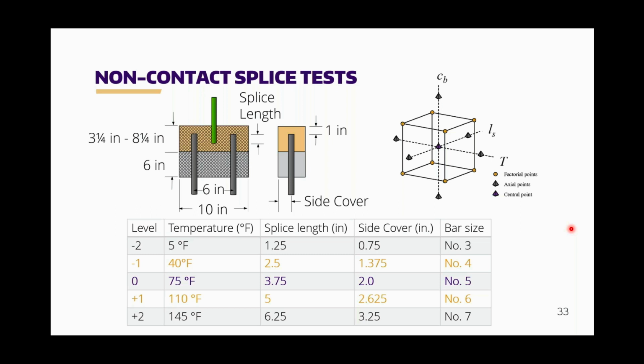For the main chunk of this non-contact splice testing, we used a fractional factorial design. Pretty much that means you have repeated center points within each of your batches to ensure that you have consistency between each batch. And then you're modifying each of your variables to create your axial and factorial points. This all sounds very fancy. It just gives you the ability to statistically analyze it in a way that's easy and provides good results. So the 4 variables that we looked at for these non-contact splice tests were temperature, splice length, side cover, and bar size. When I say bar size, I'm referring to the epoxy-coated bar, so the green one in the figure there. And then we followed a similar temperature range, going a little bit hotter than we did for the mechanical properties. So we ranged from 5 degrees Fahrenheit on the low end to 145 on the high end.